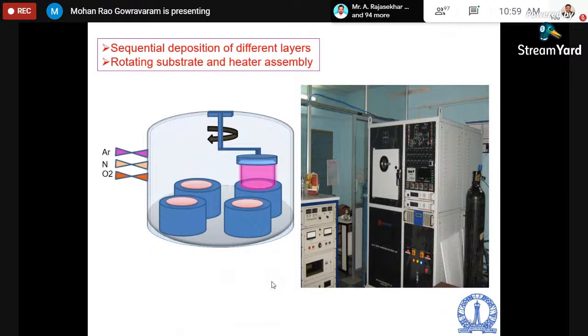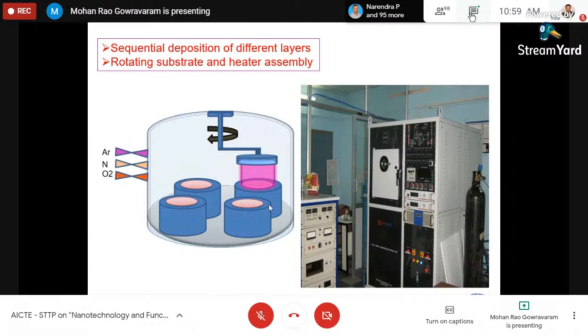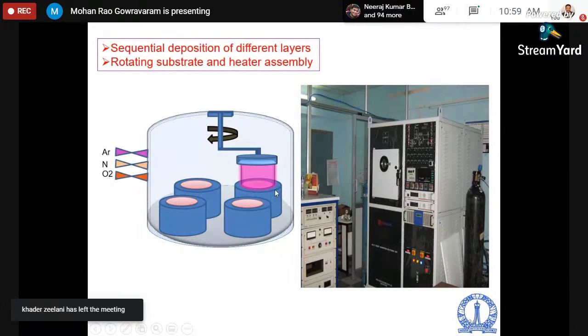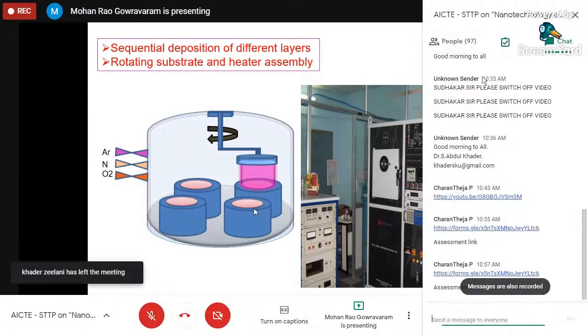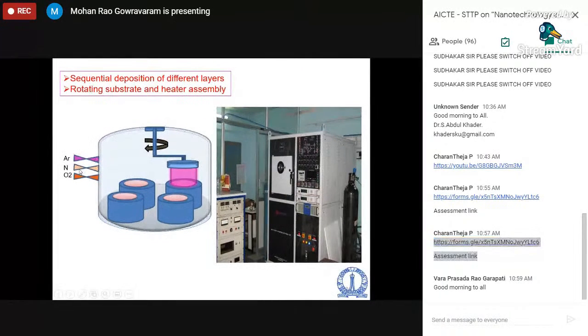So this is a typical sputtering system which is having 4 cathodes. So cathodes are having the material that you have to deposit in thin film form, and on the anode you keep your substrate or the wafer, which could be rotatable so that it moves from one target to the other target. So you start with metallization first, then cathode layer, then the electrolyte layer, then the anode layer, and then come back to metallization. And the gases that you are using are argon for striking the plasma, nitrogen for